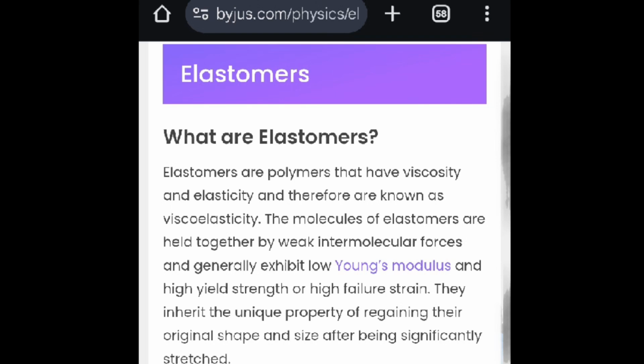And why does that matter? We talked about elongation being how much it can stretch. To qualify as elastomeric, as we originally discussed the definition, the minimum standard we were able to find is that it would have to be capable of stretching to 2 times its size, which is an elongation of 100% minimum, and then go back to its original shape at room temperature.